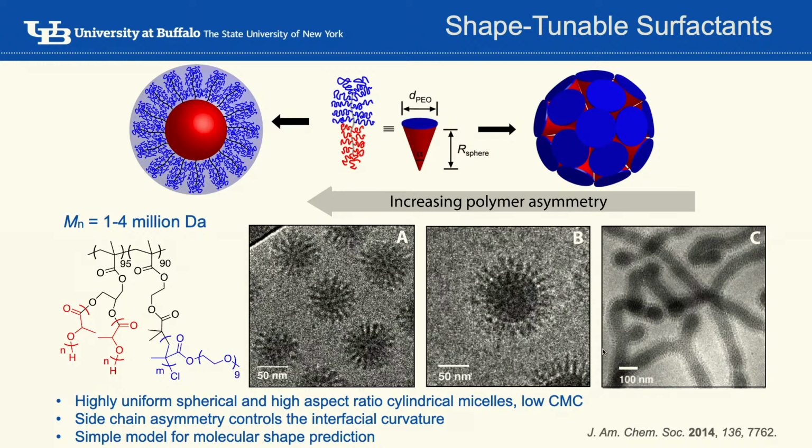This is similar to surfactant self-assembly, where one can calculate packing factors and predict the morphology. We've developed a model for these molecules to predict the morphology as well, based on studies on small surfactants. These are all dilute solutions. If you do it at higher concentration, you will start forming different morphologies. You can get lamella, so we've done lamella as well. If it's more symmetric, lamella morphology in solution would form a bilayer vesicle.